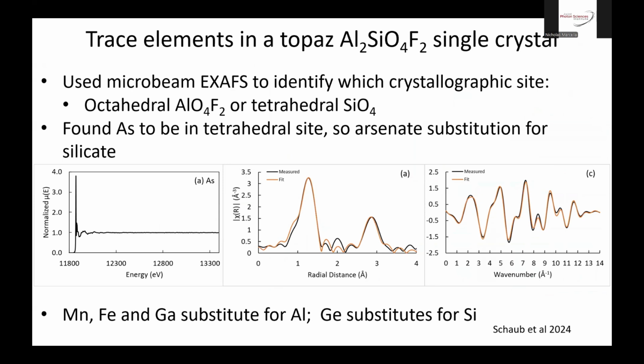And a third, very different example is a study of trace elements incorporated into a single crystal of topaz. This is from a local geologic project. So we used microbeam XAFS to identify which crystallographic site, either the octahedral aluminum site or the tetrahedral silicon site, was the host for various trace elements. And interestingly, as shown here, we found that arsenic was substituted into the tetrahedral site. So it's essentially arsenate substituting for silicate, which is relatively unusual in geologic systems. We also found that manganese, iron, and gallium were substituted for aluminum, while germanium substitutes for silicon. So this was done by microbeam XAFS, and that was published last year.